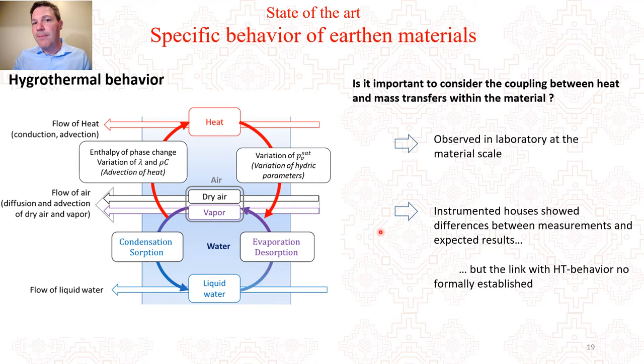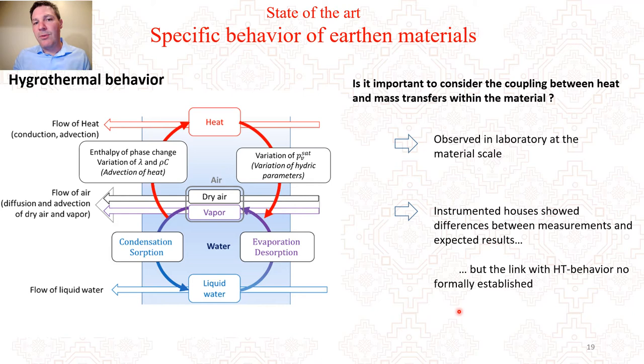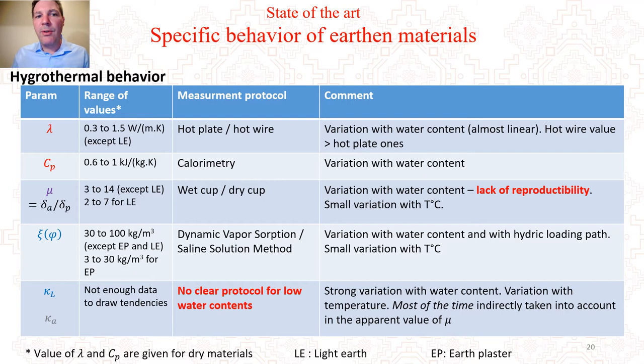This coupling has been observed in laboratory, and an impact has been really observed when instrumenting earth houses, where we have seen some important difference between the expected thermal behaviour and the actual behaviour. However, right now it is not yet proven that this difference is only due to the hygrothermal process, so research must be continued. If we want to model the hygrothermal behaviour of earth construction, we need to know the key parameters: thermal conductivity and heat capacity, the effective vapour diffusion through the material (or µ, the ratio between the free diffusion coefficient and the diffusion coefficient within the material), and the isothermal sorption curve.